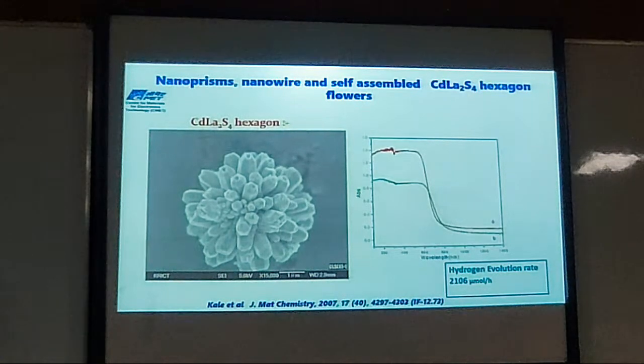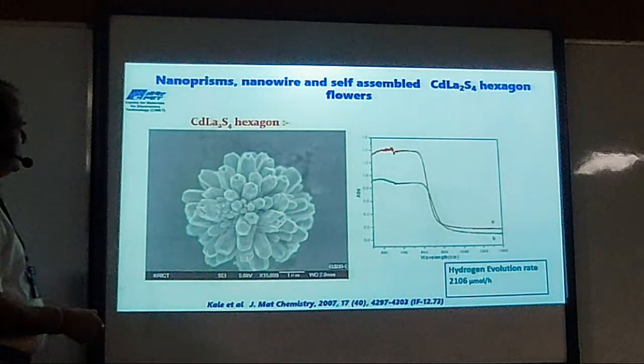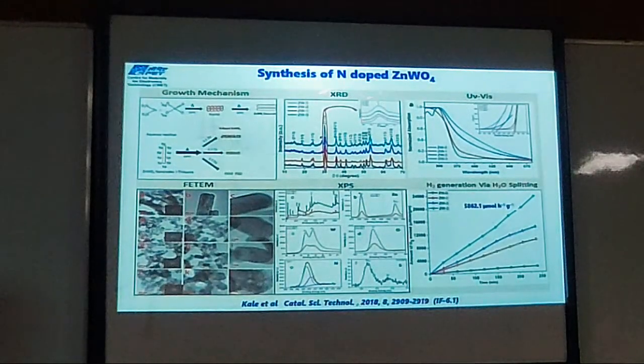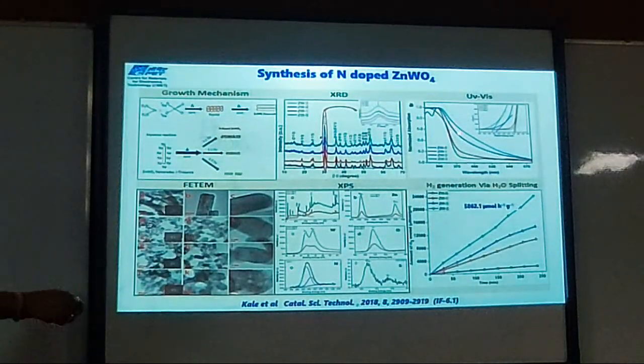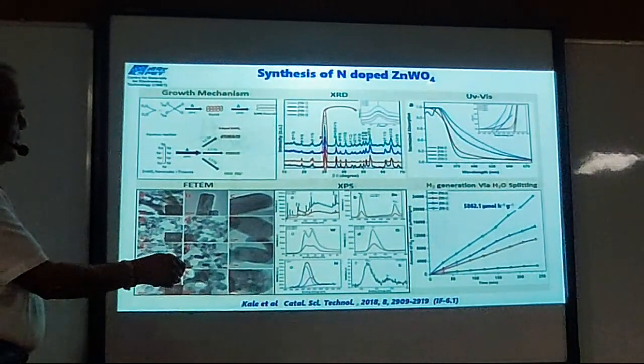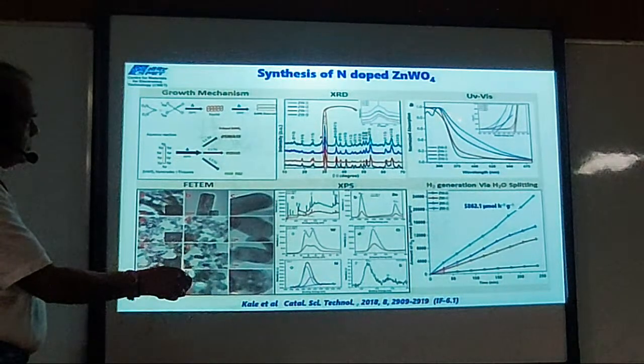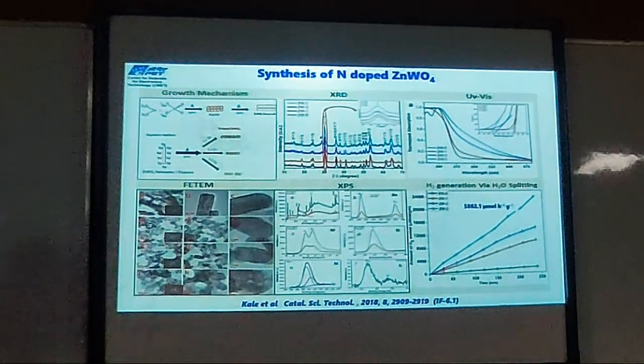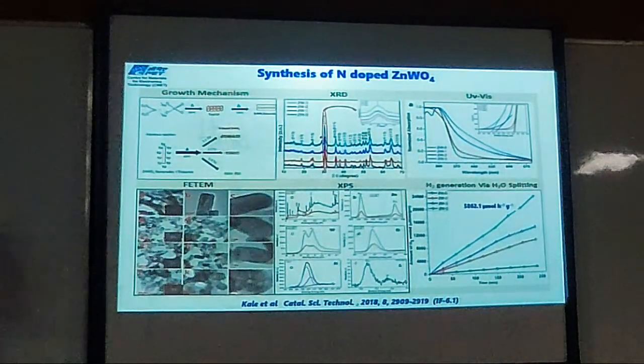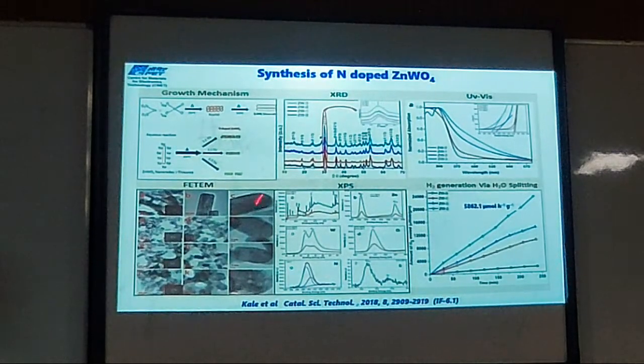And since it's a new catalyst, we did some simulation. Then ZnWO4. These are the latest things we have. ZnWO4 has a band gap in the very UV region. You see, here their absorption is at 375. When we dope with nitrogen, their absorption is increased in the visible region. Why have we selected ZnWO4? It's a highly stable compound, and we found that this is one of the good ZnWO4 nanorods.